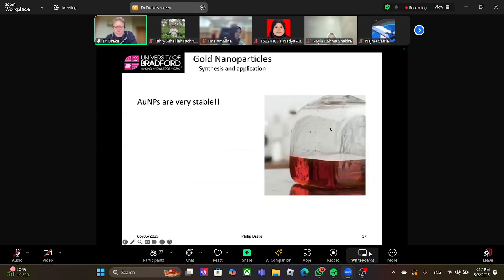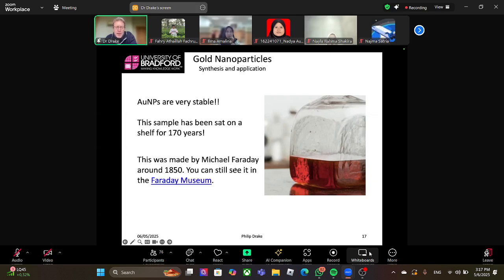When they're made, gold nanoparticles are very stable. Here's an image of some gold particles in a glass vial. You can see the red color, characteristic of 10 to 20 nanometer particles. This sample is 170 years old and it's still stable. They're still well dispersed nanoparticles in solution. It was actually made by Michael Faraday back in 1850. If you go to the Faraday Museum in London, you can see these on the shelf.